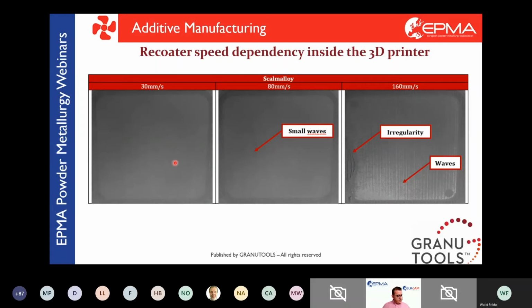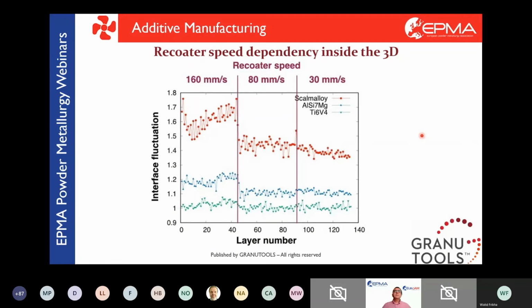And so we put those 3 pictures inside a software that we call the granulator. The granulator gives us the interface fluctuation of the powder. Do not pay attention to the layer numbers, it's not an important parameter, but what we can see is the interface fluctuation of the powder bed.